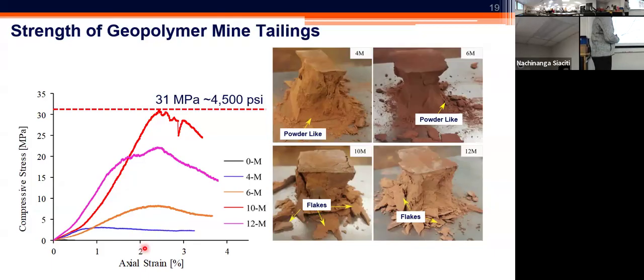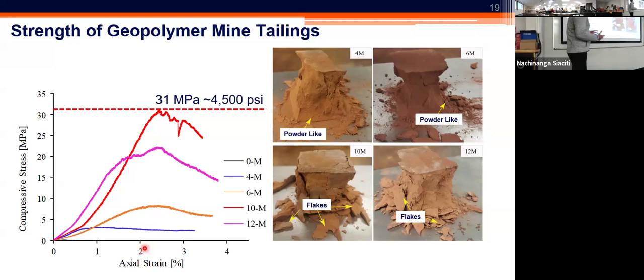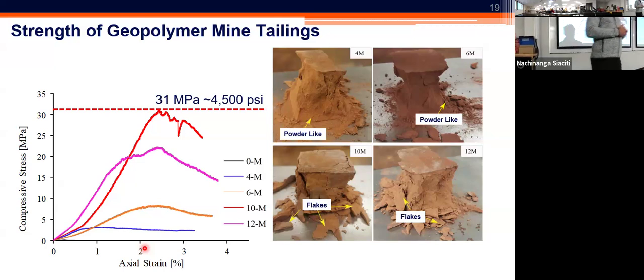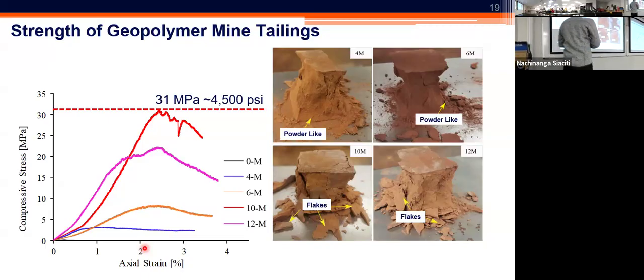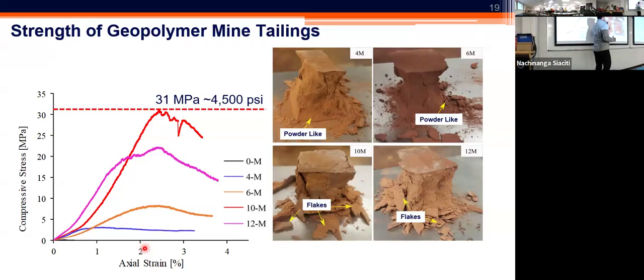Right now in our laboratory, we are seeing some strength levels that are almost 3 times these values. But again, the success and the performance highly depend on the mine tailings and the kind of aluminum silicate species that are available. But what if we tend to geopolymerize the material, but with an insufficient molar concentration or the wrong chemical type of activator? Well, if we do that, as shown here, we not only get fairly lower levels of strength, but also the mine tailings remain in their original form. So when the sample breaks, you start to see those powderized mine tailings that are still available. But when we do sufficient geopolymerization, the material no longer looks like the original raw form. In fact, you start to see a concrete, brittle-like material that is visible from these images.